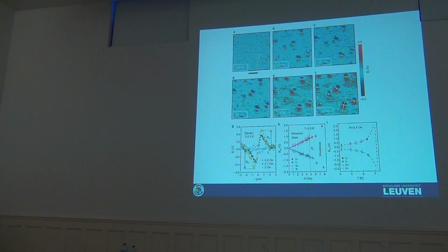And I repeat, there is no contradiction here with the fluxoid quantization, because any closed contour embracing the pinning center encloses both vortex and antivortex in this dipole, and it's plus something minus exactly the same, and then this is 0, and 0 is also an integer. And if you have a closed loop outside here, then none of them is enclosed by that loop.